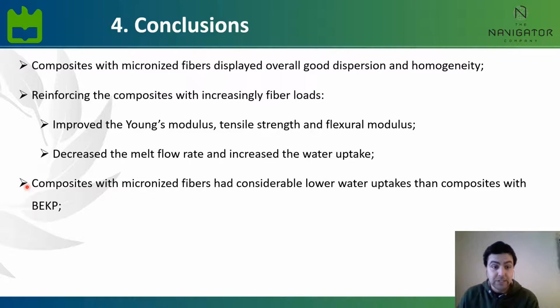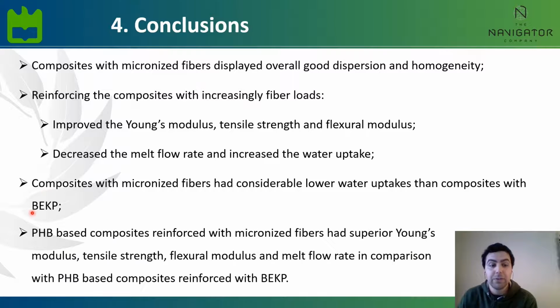We can also conclude that composites with micronized fibers had considerably lower water uptakes than composites with the non-treated bleached eucalyptus kraft pulp, and the PHB-based composites reinforced with micronized fibers had superior Young's modulus, tensile strength, flexural modulus, and melt flow rate in comparison with the PHB-based composites reinforced with the non-treated bleached eucalyptus kraft pulp.